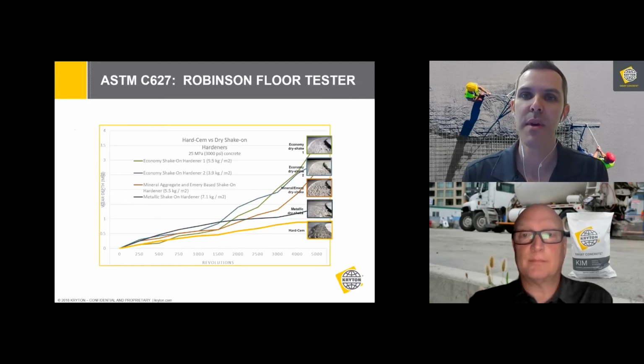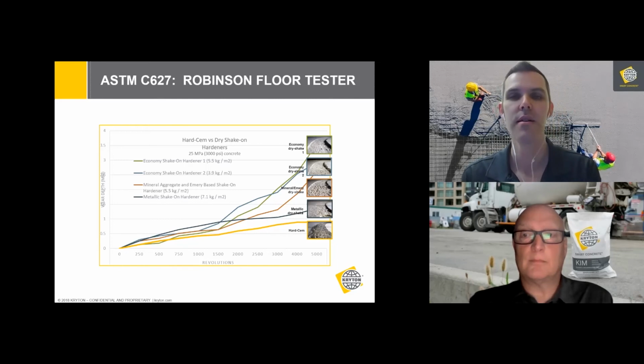And again, because this test method gives you nice large test panels that really recreate the finishing techniques that would be used in the field, it's also the ideal test method to compare Hard-Cem to some of the other technologies we were talking about earlier. So looking here, a test program was performed using Hard-Cem, comparing it to some of the common dry shake products that are on the market. Now, among the dry shakes, there's a range of materials, as you might expect. Some work very well, some not as much. But what you can see is that by using Hard-Cem, not only are you still getting top abrasion performance, consistent with the best dry shakes on the market, but you're still getting this in a product that is much easier and much more reliable to install. So you're actually a lot more likely to achieve that performance in the field.